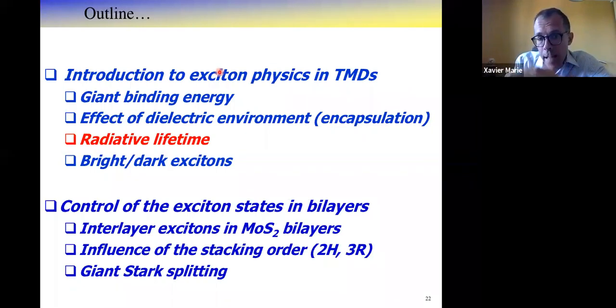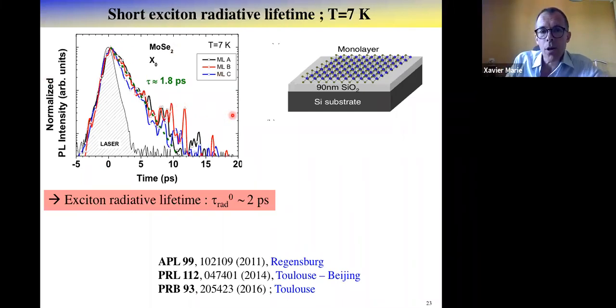So now, again, an important consequence of the fact that when you do optics with these materials, basically you deal with excitons, and so the lifetime will be controlled by the recombination of the exciton. So what about the radiative lifetime? And so we have worked on this for many years, and here is a typical experiment where we have done time-resolved photoluminescence spectroscopy with an ultrafast detector, an optimized streak camera, a very fast detector. You have the PL intensity as a function of time, picosecond laser, and here you have the decay time of the luminescence, which is typically of the order of 1 or 2 picoseconds.